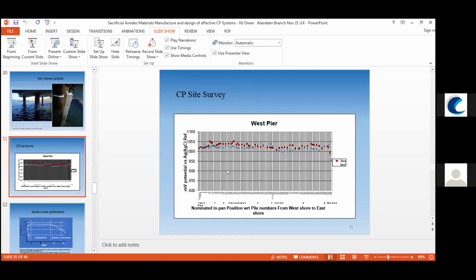Then you can survey it using a multimeter and a reference cell. You're able to run along and see whether you've actually got the protection level that you want. So you can walk along, say, the top of a pier and contact the pile and use the reference cell on the, say, the in pans, and do that at the bed level and the mean sea level, and you get a distribution, a variation. Some of these variations are real, some of them to do with positioning, and some of them maybe to do with seabed variations, etc., and also tailing off towards corners and towards drains where there aren't any materials installed.